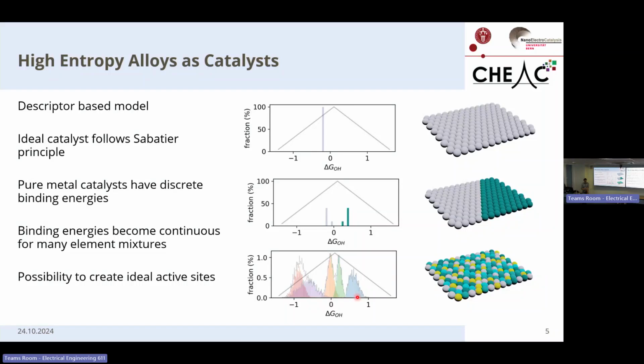But when it comes to catalysis, in general, that doesn't matter, because if you bind a catalytic intermediate on one side, for it to diffuse to another side, you need to invest energy. That would also go into your reaction energy, having this migration over the surface, and would account for the same energy as straight adsorption. So whether your reactants can diffuse freely over the surface or not will not really change the catalysis.